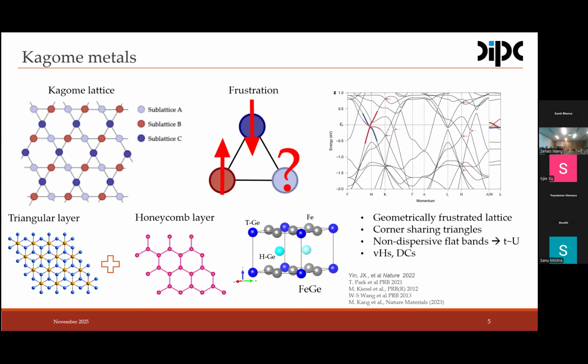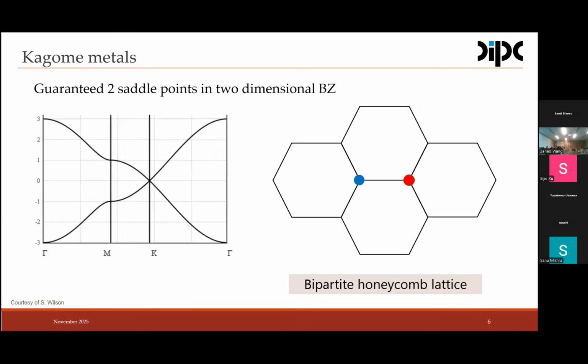One way to understand this band structure, which is actually very complex, is that these Kagome materials are multi-band, multi-orbital systems with a lot of bands crossing the Fermi level. One way to easily understand that is starting from a honeycomb lattice. The honeycomb lattice has two sites per unit cell, which I show here. The energy spectrum of this honeycomb lattice is characterized by two van Hove singularities at the M point that cross linearly at the K point. So if now we connect